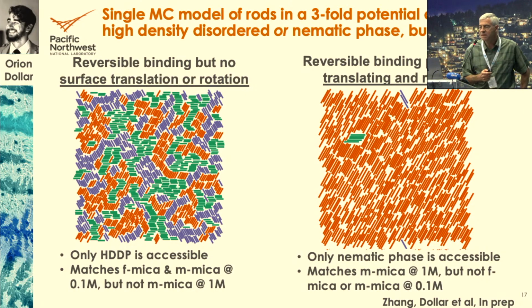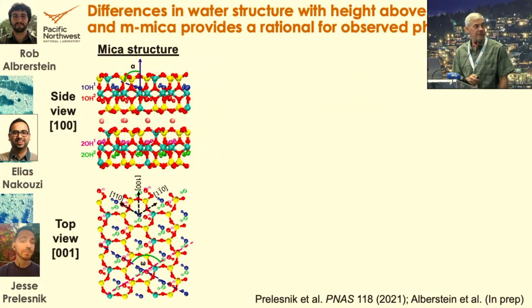So how is it that we can get a difference between fluorophlogopite and muscovite, where fluorophlogopite is apparently here and muscovite is apparently here at high salt concentration, but between fluorophlogopite and muscovite, they're both mica? But if we go from high salt to low salt on muscovite, we go from here to here. And the answer turns out to be incredibly surprising and important. What is the difference between fluorophlogopite and muscovite?